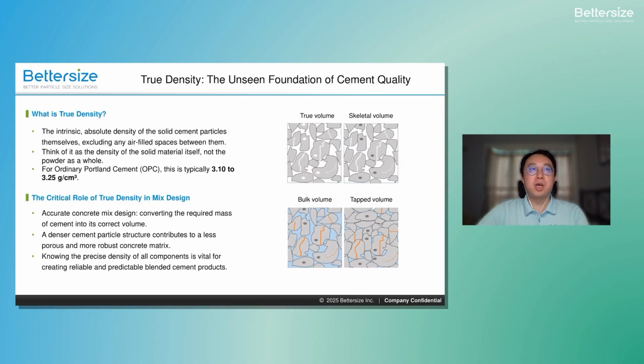Among definitions of density of powder materials, true density is the density of the solid particle itself, with all the pores and air spaces excluded. For cement, we can state that its true density is effectively equal to its skeletal density, because unhydrated cement particles are generally non-porous and free of any closed internal holes. This allows us to confidently benchmark the value of a typical OPC between 3.1 and 3.25 grams per centimeter cubed.